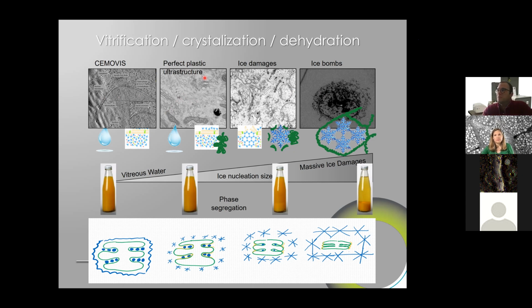Then we start to see the ice damage, where the segregation starts to become stronger. Then we have ice nucleation, which excludes the proteins, so you have a very dense protein region around a white core, and you start to have a more crispy aspect in the images. That's the beginning of bad crystallization, bad vitrification. And then of course, there's the obvious case of a very disastrous freezing, where you have ice bombs everywhere, ice crystals and dry matter all around. This looks disastrous, and unfortunately we've all seen that once if we've done some high pressure freezing or vitrification.